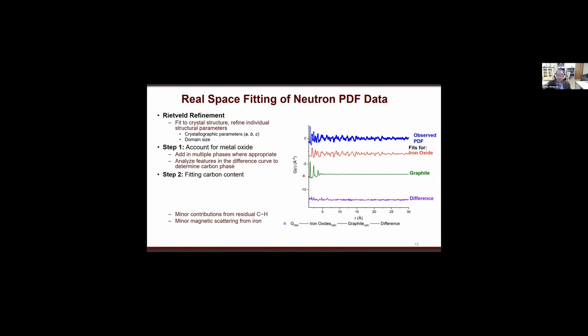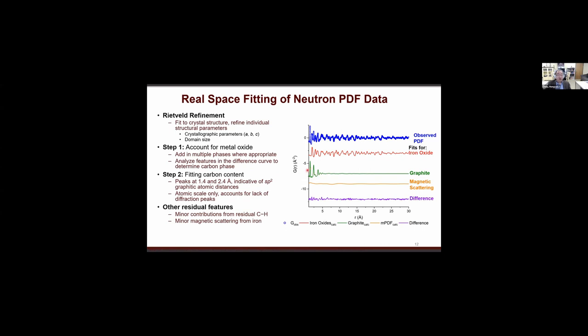So here is the carbon phase. The green curve here is graphite, and this is typical for graphite. Depending on the domain size, you may see more features here. And then fitting the carbon content: how do you do that? The peaks at 1.4 and 2.4 angstroms are indicative of sp2 graphitic atomic distances.